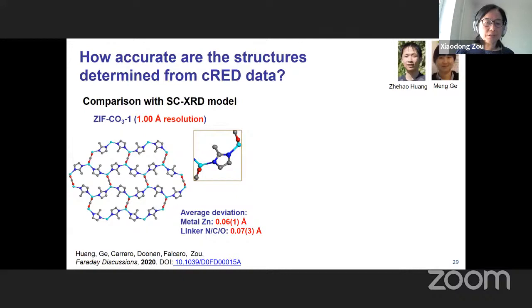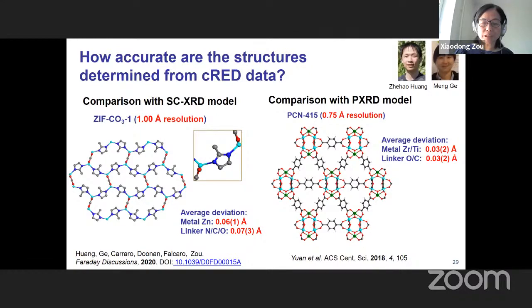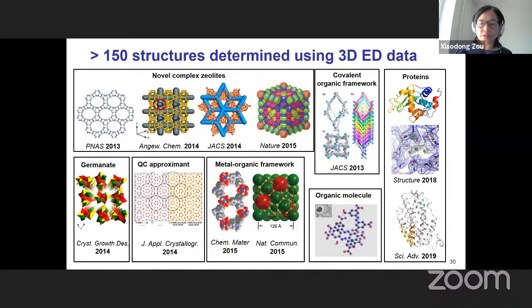And how accurate it is depends on the resolution. So in this case, we compare the structure, a metal-organic framework, with the single crystal diffraction model, and it has an accuracy of 0.07 to 0.06 angstrom. And if we combine it with the powder X-ray diffraction, it's 0.03 angstrom in average distance, so they are quite reliable, even though we use electron diffraction data. This means that electron diffraction now can be a very good method for structure determination, in the same way as X-ray diffraction. And these are the different sample materials we developed and determined using electron diffraction data.